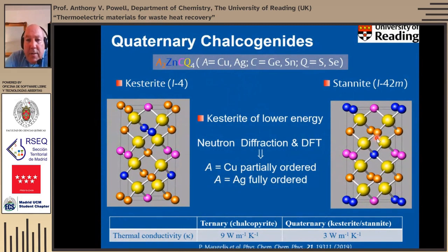These are very difficult to distinguish by X-ray diffraction, and there's a lot of confusion in the literature, and we've written a whole paper on identifying which are the stable phases for different compositions. I won't go into that lengthy story now, but just to say that a combination of neutron diffraction and DFT shows that it's the kesterite structure. When A is copper, it's partially ordered, and when A is silver, it's fully ordered.